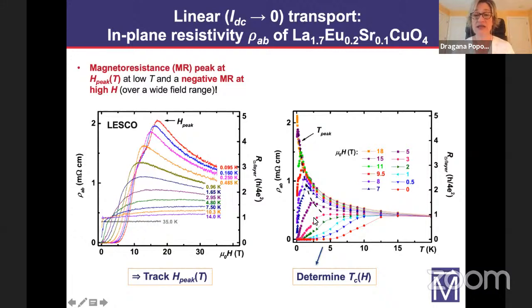And we also notice that once TC goes to zero, we start seeing a peak in the temperature dependence. So some curves that wanted to be insulating-like actually turn down at lower temperatures in a metallic-like or superconducting-like fashion. And this position of the peak also shifts with the field, so we decided to track that.